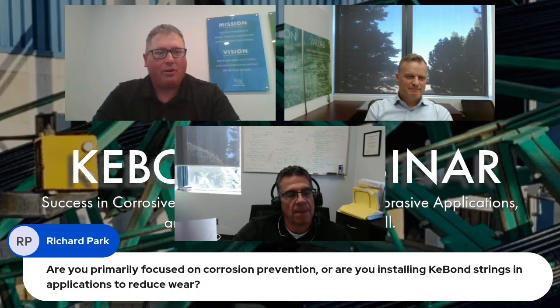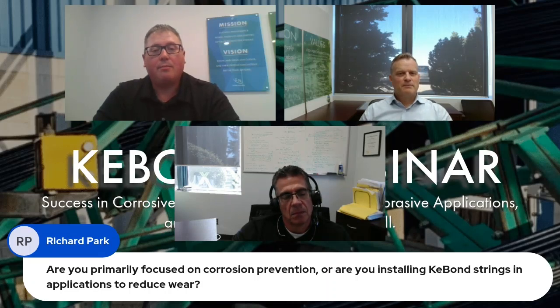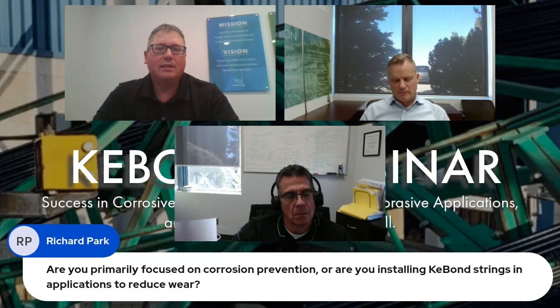Richard Park, are you primarily focused on corrosion prevention, or are you installing KeBond strings in applications to reduce wear? Yeah, we are primarily focused on corrosion prevention. I talked about this in one of the slides, we're really evaluating KeBond in wear applications. We find that sand tends to be very aggressive with the plastic or the polyketone coatings. Sand can get embedded in line tubing. Sand can get embedded in these coatings, and you can see some higher wear rates there.